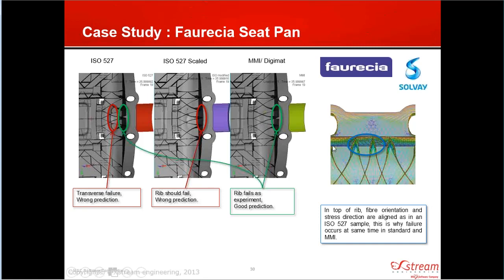Once again, if we look over at the fiber orientations, we can see why this is happening. Along that rib, we have this very orange-colored group of fibers, and those fibers are aligned in the direction of loading. So they're going to be very, very stiff relative to the last scenario that we're looking at. That's why you can capture this failure in both the isotropic approach, where you have a very stiff material model all around, and the Digimat approach. Because in the Digimat model, you're going to have soft material where it's actually soft, and stiff material where it's actually stiff.